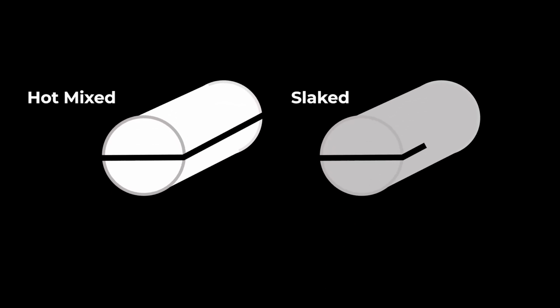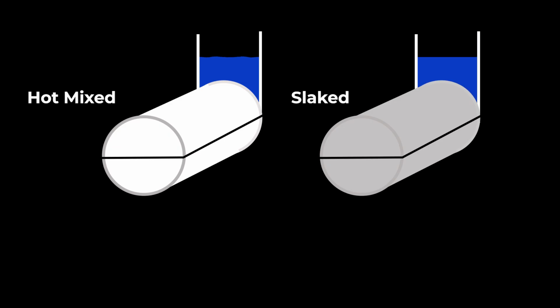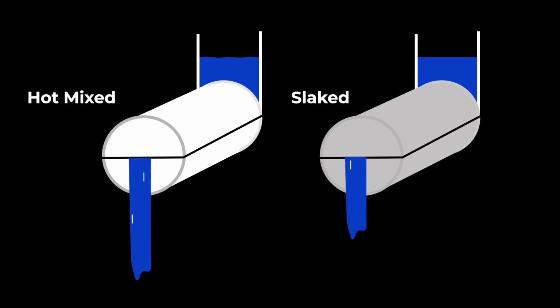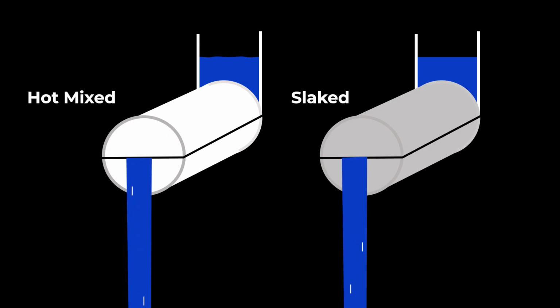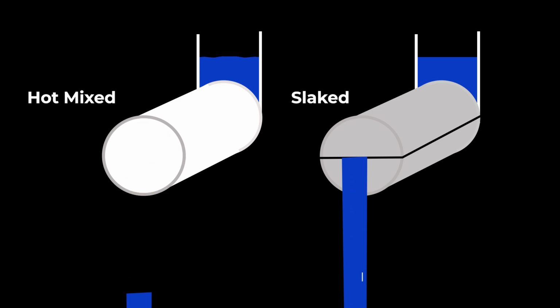As a final test, the researchers split each concrete column down the middle and remated them together about a millimeter apart. They then set up a pump system to continually flow water through the gap between each side of the concrete. Would it also have those elusive self-healing properties? Amazingly, just a few weeks in, the team had noticed that the system had automatically shut itself off. Water had ceased to flow through the hot mixed concrete sample. The control samples without the quicklime were left to run, but never repaired themselves.